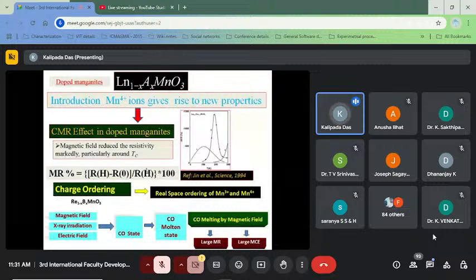But when this trivalent site, for example the lanthanum site in LaMnO3, is doped with some bivalent element, that means calcium, strontium, etc., then the valency state of the Mn, which was previously Mn3+ in the undoped case, will be converted to Mn4+ in the same percentage as the doping, and this introduction of the Mn4+ ion gives rise to new properties. A very interesting property is the CMR effect in doped manganite, the colossal magnetoresistance effect. The magnetoresistance is manifold enhanced in the doped manganite system with respect to its parent undoped compound.